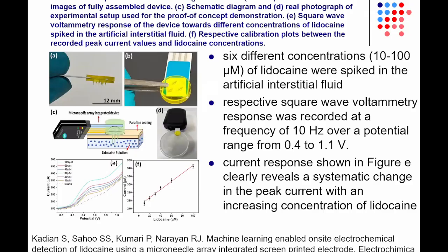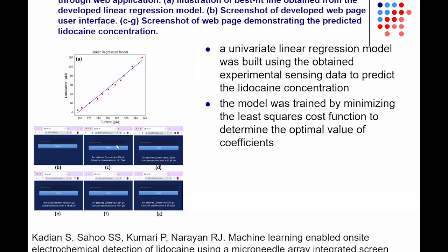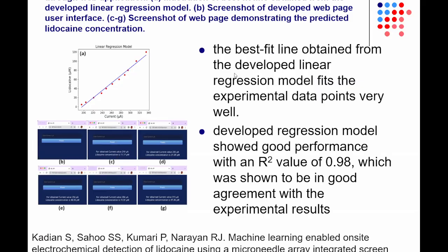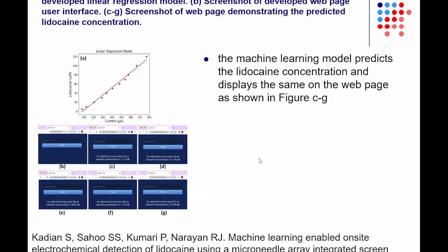Here you can see a little bit more data that was obtained in a human-like situation where you have a lidocaine solution, a parafilm seal on top, and you apply the microneedle interface to that through the parafilm seal to interact with the lidocaine solution. So here you can see how machine learning can be used to understand the data. Your regression model was used to fit the experimental data, and it fit the experimental data very well with an R-squared value of 0.98.